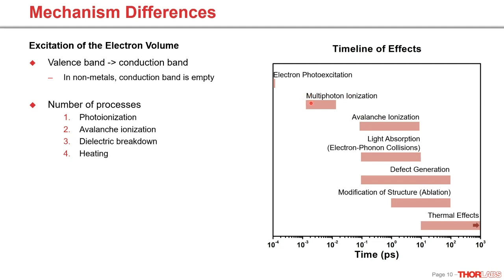And you can see that that is reflected in this graph where we see multi-photon ionization occurring relatively soon after the impact of the light, and then you're going to get avalanche ionization, you're going to get the electron phonon collisions that I just referenced, and then you're going to get defect generation and ablation of the structure. You're not going to start to get thermal effects until about a picosecond after the laser is there. So this is why, as I referenced earlier, you're going to see less heating from the shorter pulses.